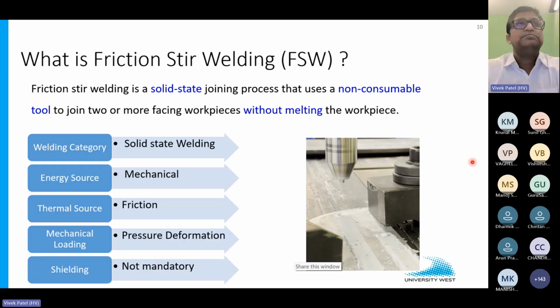So if we categorize this welding process, it is solid state, so you work at less than 90% of the melting point of the material, and the energy source is completely mechanical force. So you apply a significant amount of force downward, and the force varies from material to material and from thickness to thickness, whatever you want to weld. And the heat source, or thermal source, is nothing but the friction between this tool and the workpiece.